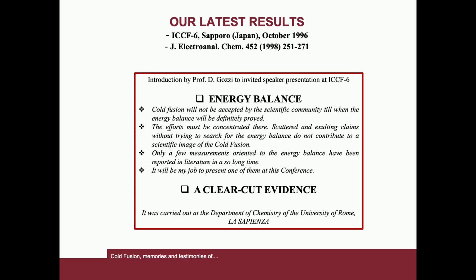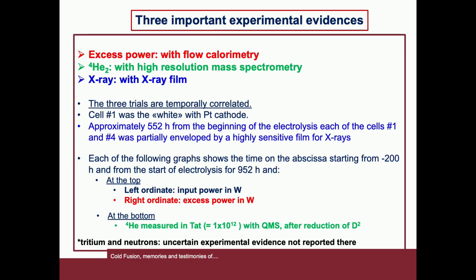I announced that shortly thereafter I would show the attempt that we made in the direction of the energy balance through three important quantitatively evaluated experimental evidences. What were the three important experimental findings? The first is the measurement of excess power by flow calorimetry. The second, the measurement of helium-4 by high-resolution mass spectrometry. The third is the impression of a film for X-ray with evaluation of the energy involved after calibration with a standard camera for X-rays. An important aspect is the time correlation of the three phenomena.